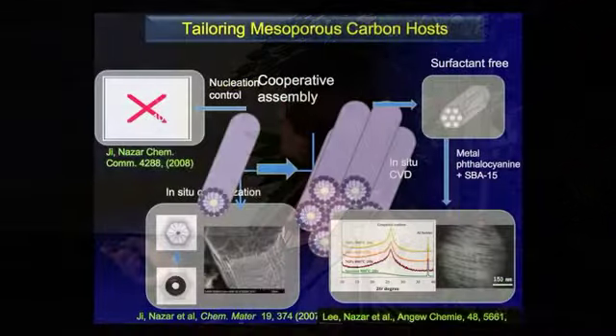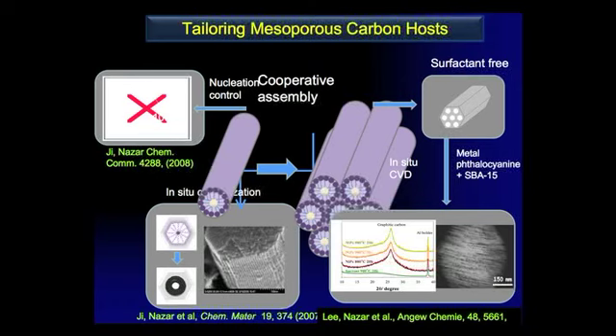If you control nucleation of these systems well, you can end up with nano versions of these mesoporous materials. You can in situ carbonize the surfactant rather than having to extract it and stuff in carbon afterwards to obtain relatively highly ordered materials. This is a catalytic carbonization process. And we've also used things such as metal phthalocyanine to produce fairly graphitic versions of these materials, where you can see the graphitic peak in the X-ray diffraction pattern, compared to that of using sucrose, for example, for stuffing. So these are just some of our initial attempts.